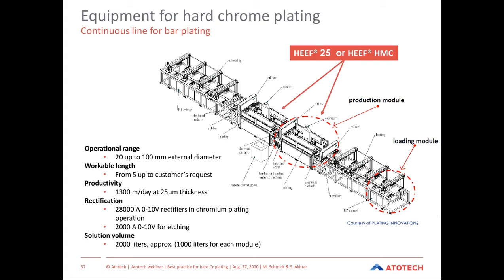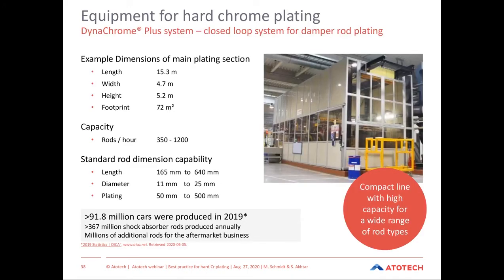These kind of systems can plate up to 1,300 meters per day of hydraulic bars. And this happens with a volume of only 1,000 to 2,000 liters in each module. So the amount of chemistry is significantly reduced in these kind of machines.